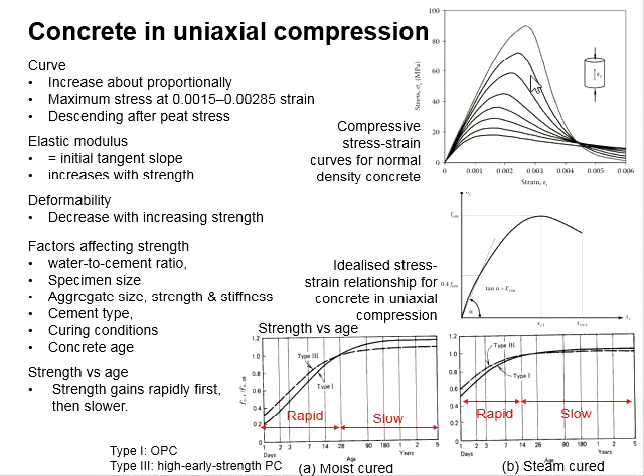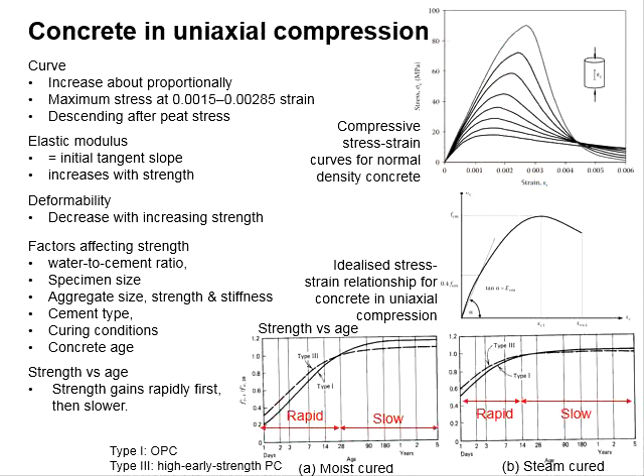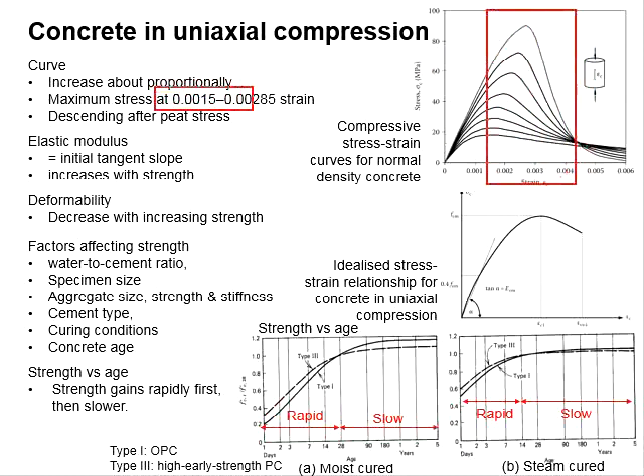What you can see here is that stress increases approximately proportionally to the development of strain in concrete. The maximum stress occurs somewhere between 0.0015 to 0.00285 strain.